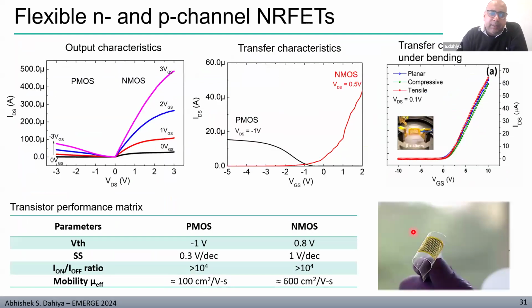This is the performance extracted from these transfer characteristics, a summary of both P and NMOS. We can reach device mobility of around 600 for N channel and 100 for P channel devices. Threshold voltages are positive for NMOS, which is good for normally-off devices, and on the negative side for PMOS. On-off ratio is more than 10^4 for both of the devices.